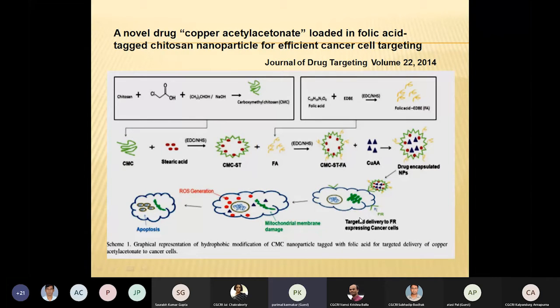And then we also explored whether this can kill the cancer cells and what the mechanism is, because you know that induction of necrosis is not welcome, and even the induction of pyroptosis or any other kind of death apart from apoptosis is not welcome. So we analyzed and found that it can induce damage to the mitochondrial membrane, resulting in the production of a huge amount of reactive oxygen species, which mediated induction of apoptosis, which is a non-inflammatory response inside the cells. And we did both in vitro and in vivo studies.